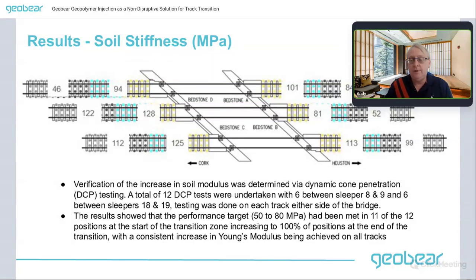So there's only one point where the starting modulus was under 50, this one over here at 46. All other points started above 50, and in all points the modulus ended up above 80 by the time you got to the actual bridge abutment. So overall, we'd met our project brief on the actual stiffness.